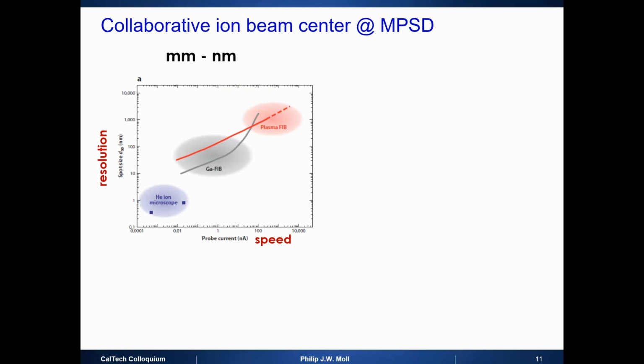It's a single atom sputtering event. So this technique is slow. To make it faster, you just need more atoms. To have more atoms, you need to open up your aperture, you make your beam broad, and you lose resolution. Clearly, you have to pick your battles. And over many, many decades, this field was dominated by the gallium FIB, where you work in the 100 nanoamp to maybe tens of picoamps range. That's where these sources are stable. And you have resolutions in the tens of nanometers to maybe hundreds of nanometers range.